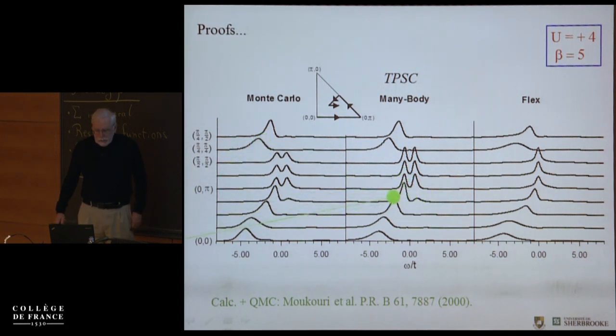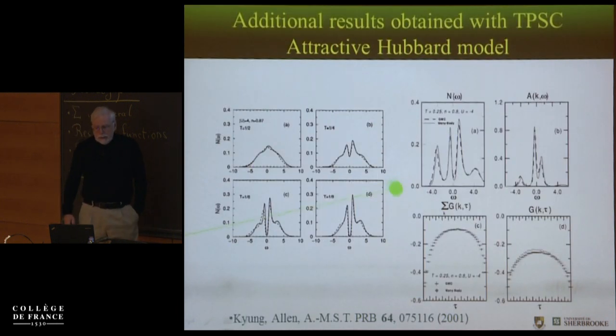This is what we get with TPSC here. We get these two bumps, and with the Monte Carlo, we get these two bumps. And the pseudogap itself, the width, the size is fine, but this is sharper in TPSC than in the Monte Carlo. If you do fluctuation exchange approximation, you miss the pseudogap. This is for the attractive Hubbard model. I don't show how to do this, but you have to generalize these ideas. And the solid line is the quantum Monte Carlo, and the dashed line is the TPSC.